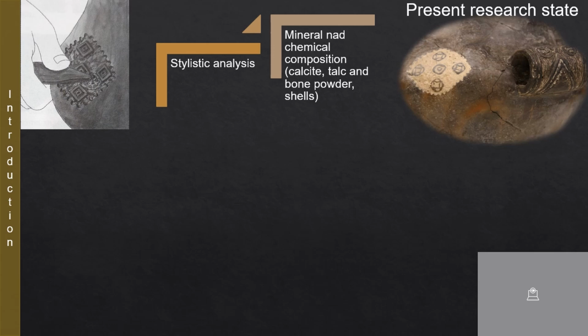In northern Italy, inlays were typically made from talc and bone powder, while in the Carpathian Basin, inlays were composed of calcite, hydroxyapatite from bones, and aragonite from mollusk shells. It has been observed that mollusk shells were predominantly used in the Copper Age, while bone became more common in the Bronze Age.